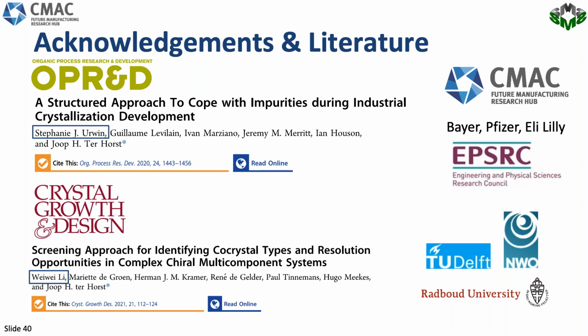Yeah, indeed. I have also seen during my previous jobs quite a number of materials that we received as wax, and it was really a matter of purification to get it into a nice crystallized powder, but it is not a straightforward thing. It's quite a challenge, and it highly depends on the compound, on the API, or what is the main compound that you're working on. Yeah, you might want to switch to melt crystallization rather than solution crystallization for low melting waxes, of course. Yes. And then you might get a better impurity rejection.